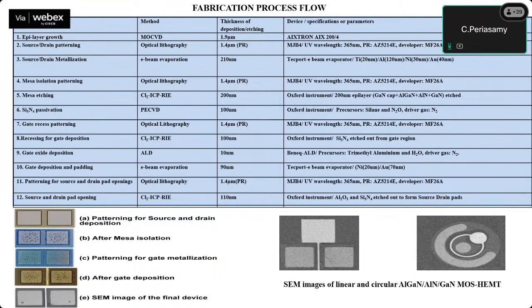And here we have created the gate recess patterning to introduce the functionalization layer. For that purpose, we have used the same optical lithography pattern: whatever optical lithography pattern we used for source and drain, the same technique we have used for gate recess patterning. Then for gate deposition, we have used atomic layer deposition, and the gate metal here is gold. Sorry, we have used aluminum oxide atomic layer deposition for the gate oxide, because in this work we have fabricated two types of devices. One is a planar structure, another one is a circular structure.